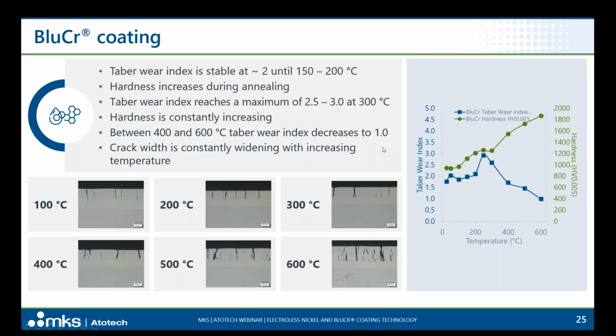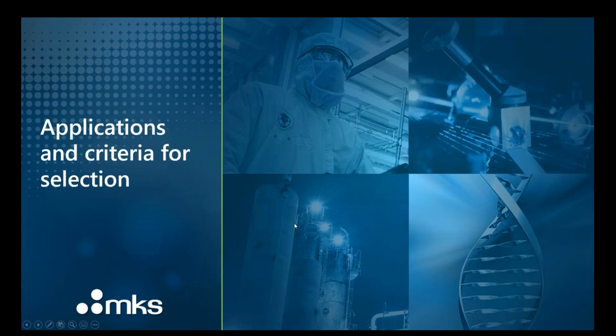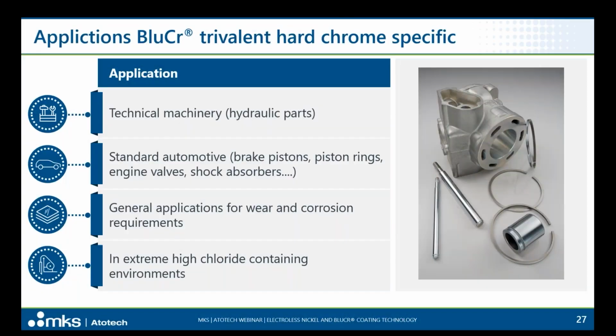On the bottom side of the slide, you can see several cross sections. So basically, these are the blue chrome layers plated on nickel on steel and subjected to different post-heat treatment temperatures. You can easily see that the crack structure changes a little bit. So some micro cracks appear at very high temperatures, and also the crack width increases, which can be beneficial for some application, like for example surroundings where the parts are in the oil surroundings, so the oil coming into these cracks, and doing that prolongs the wear time of the part.